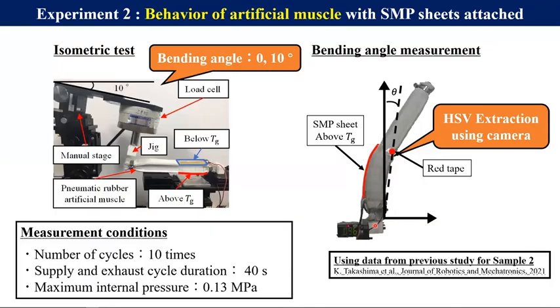In the bending test, the angle of bending of the artificial rubber muscle was measured by tracking the red tape that was attached around here. And we used the previous data for sample 2. And the measurement conditions for both of them are here.